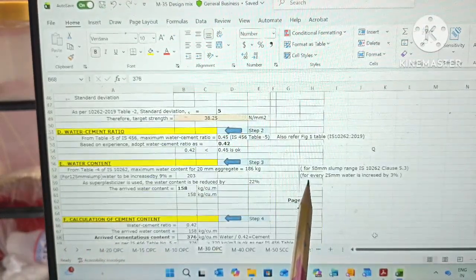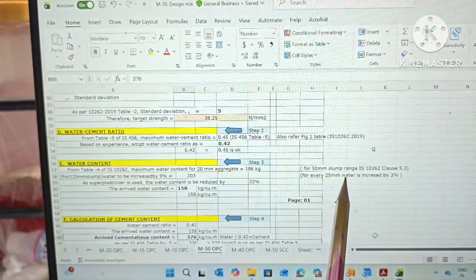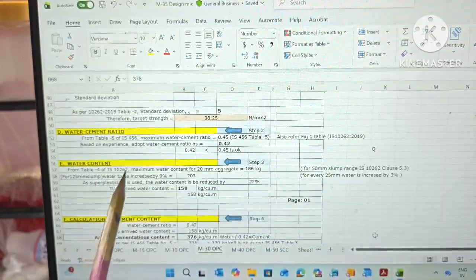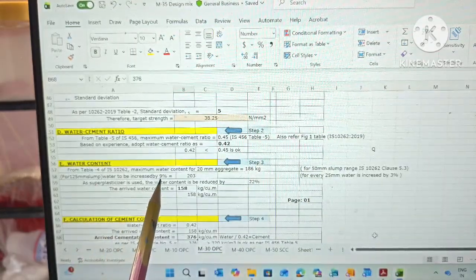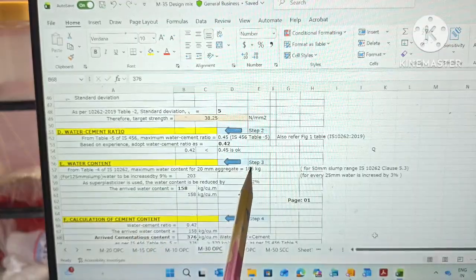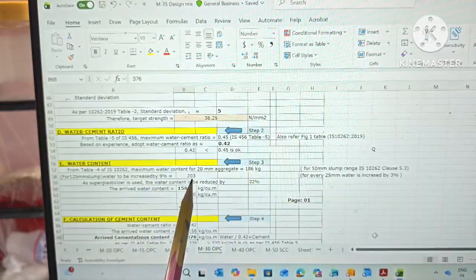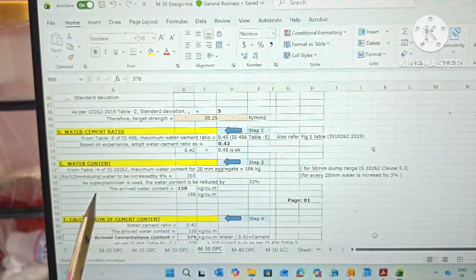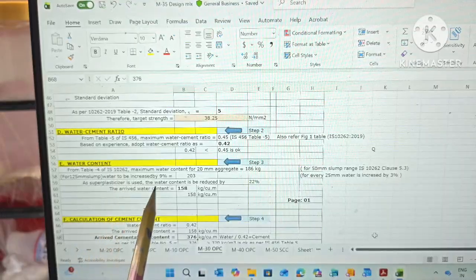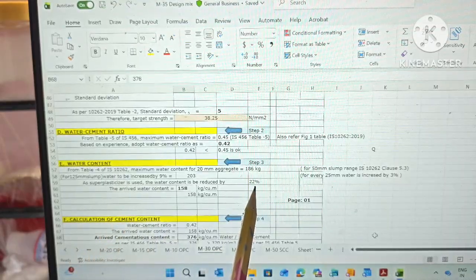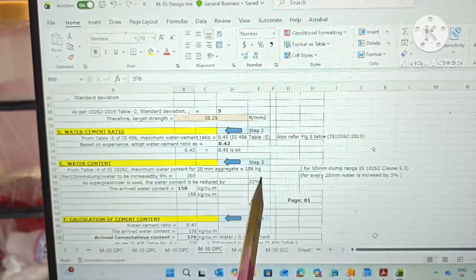It means as per IS 10262, for every 25 mm increase the water is increased by 3%, so our total increase will be 9%. So the answer will be 186 plus 9% of 186, that is 203. Now as we are using super plasticizer, the water content is reduced by 22%. Now the question is, why 22%?